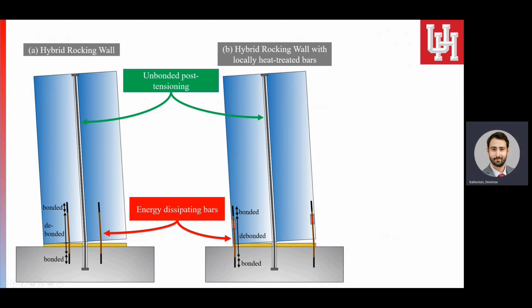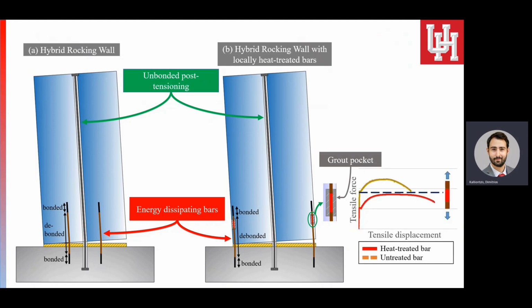So we worked on a different concept where the hybrid rocking wall uses locally heat-treated bars. In this case, the bars are similarly debonded over a region, but instead of placing them near the wall centroid, we place them near the wall ends. One modification we are introducing here: instead of having a uniform bar, we locally heat treated one section of the bar, and the reason for that is to concentrate all the hysteretic energy dissipation within this section.